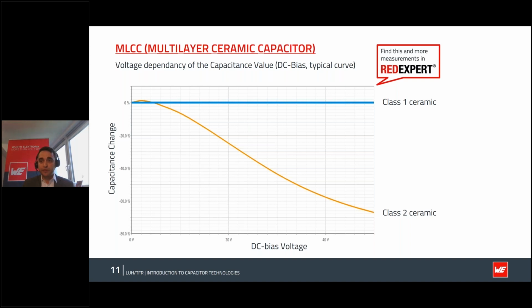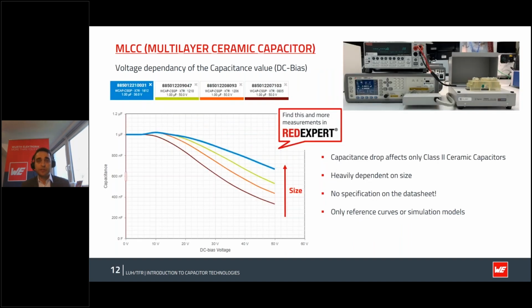And one other thing, it depends on the size of the part you use. For that I have the following measurement here. Here you can see we compare four capacitors with one another. They all have the same X7R ceramic, they all have the same capacitance value and the same voltage range. And you see here in blue, you have the size 1812, which is the biggest one. And when you go down, you see the green one is 1210. And then in orange, you have 1206. And in purple, you have 0805. And you can see the smaller the size of the part, the more significant the effect of this DC bias derating actually is.